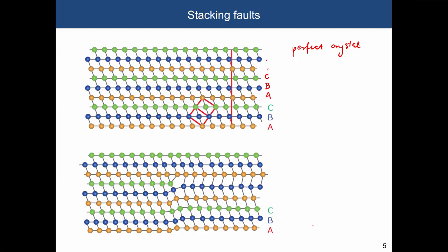And how do we know that? For example, here, we see there is the layer A, there is the layer B, there is layer A, B, C, etc. So very locally, the stacking sequence of an FCC crystal is perturbed. So this would be, for example, a stacking fault. And in this particular material, it can be, for example, formed by vacancy diffusion. So if you have a material that has a high density of vacancies, if you introduce processing, for example, by changing the temperature of the material, and if these vacancies diffuse throughout the material, they can form these stacking faults.